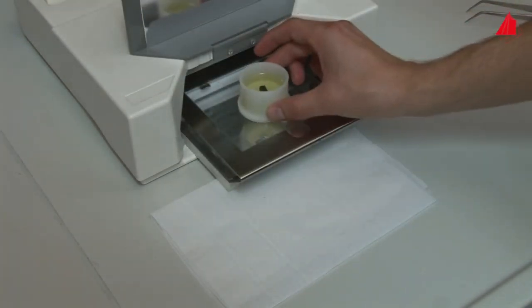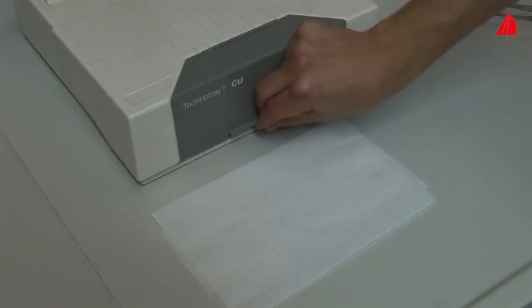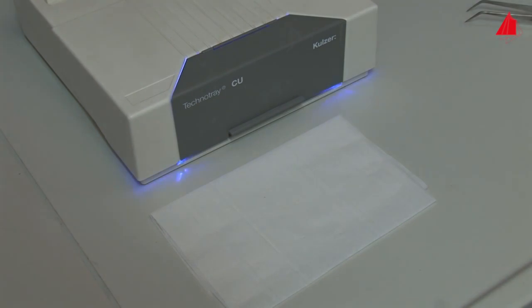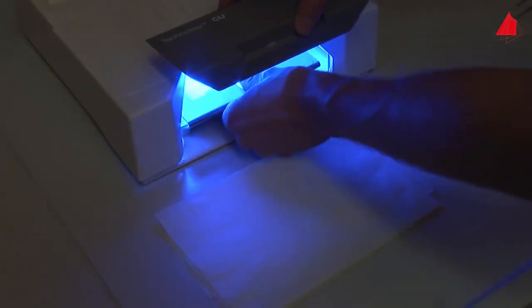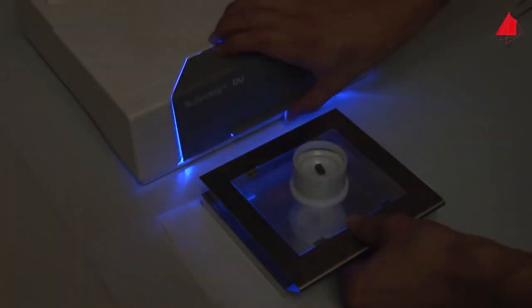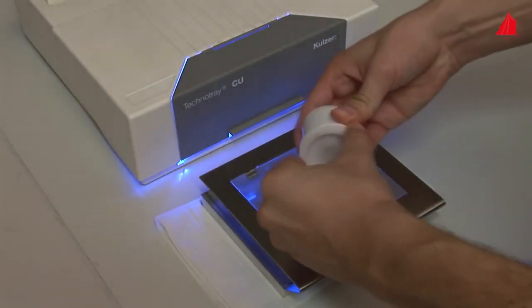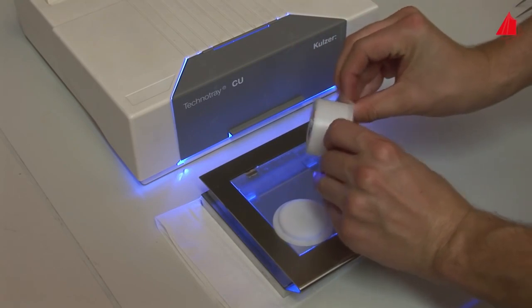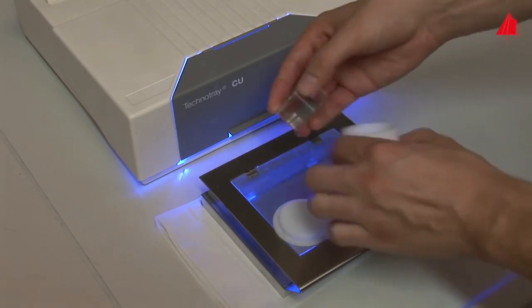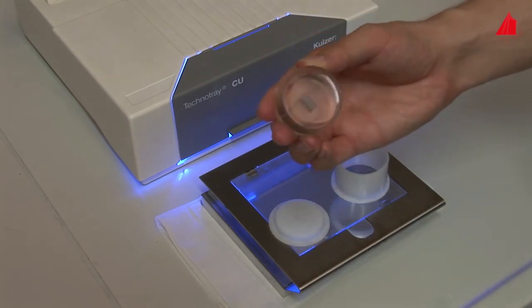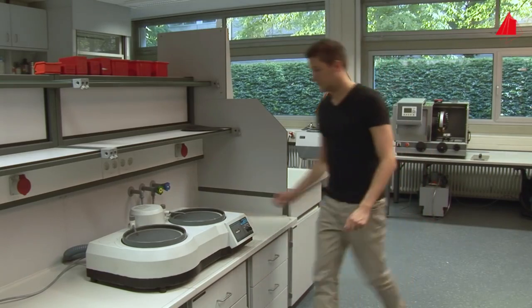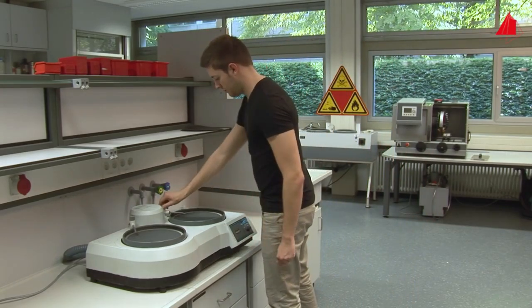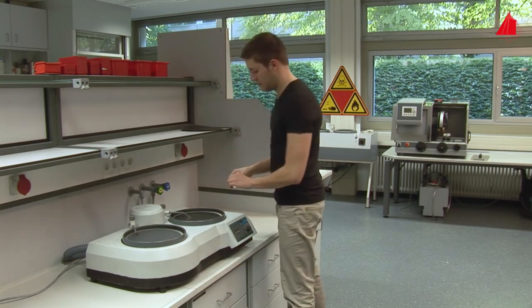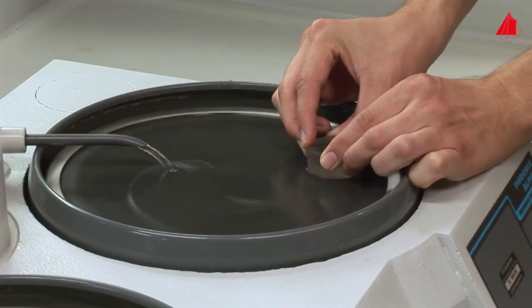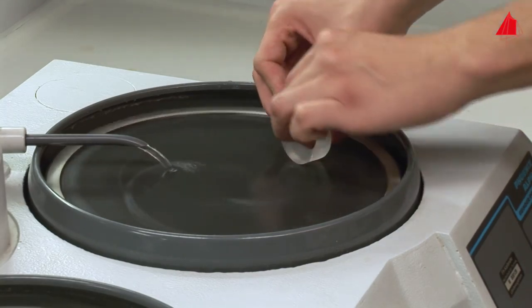Now the mold containing the specimen goes into the light curing unit. Under the action of intense blue light, the resin polymerizes within half an hour. The resin has cured and embedded the specimen well. As an alternative to light-curing resins, many other embedding materials are available. Each of them has its own advantages and disadvantages. Because the top surface is still uneven and slightly sticky, the material tester grinds it until it is even. He uses a rotating water-lubricated disc equipped with coarse-grained silicon carbide paper. The circumferential surface is slightly ground as well to ensure a clean specimen.